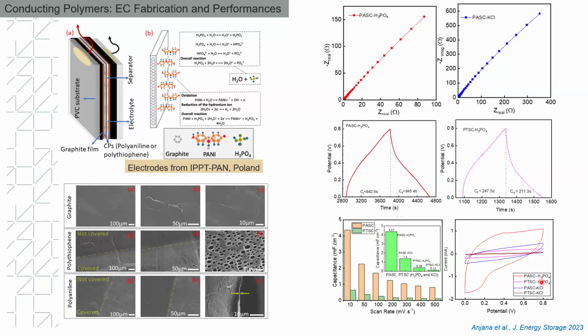We tested this with H3PO4 and KCl. You can also use this with another gel electrolyte, which we have not done yet. We are trying to focus this with different room temperature ionic liquids, because conductive polymer is one of the good materials for a flexible application, where you can easily incorporate other 1D or 2D materials to enhance its performance, which we observed previously with our metal oxide and conductive polymer combination.